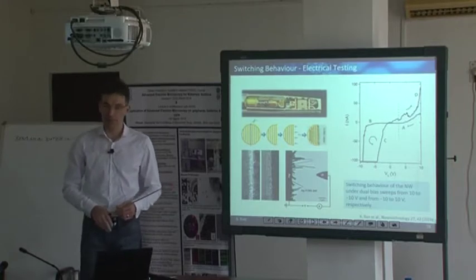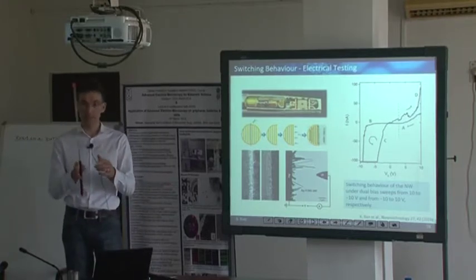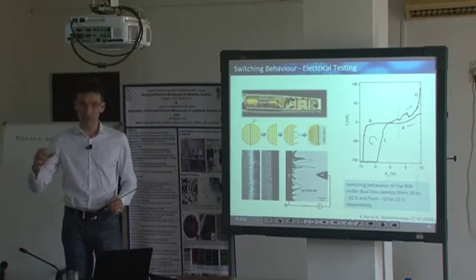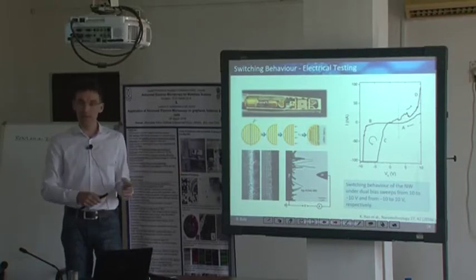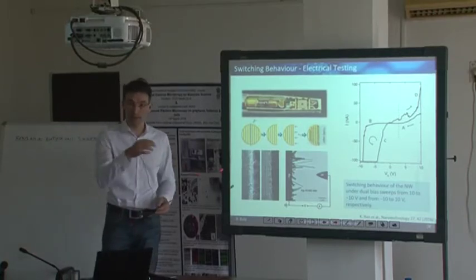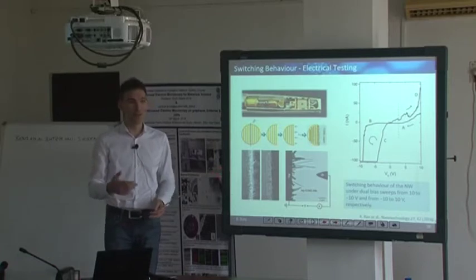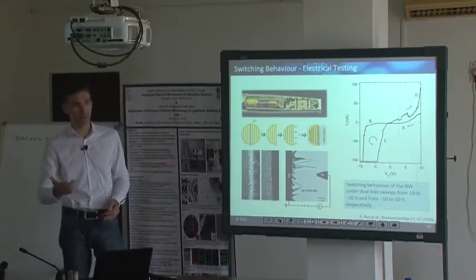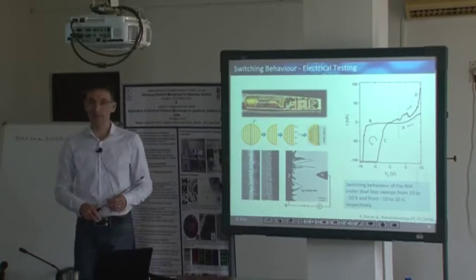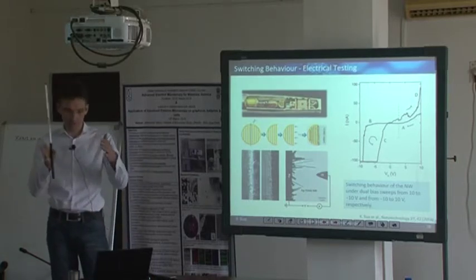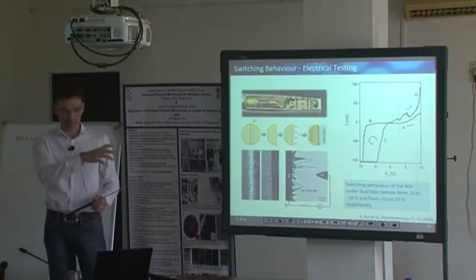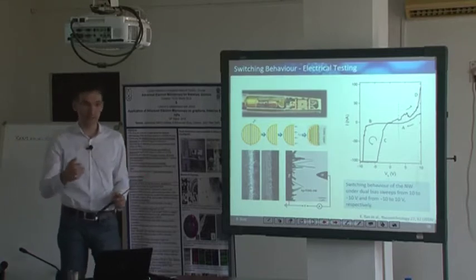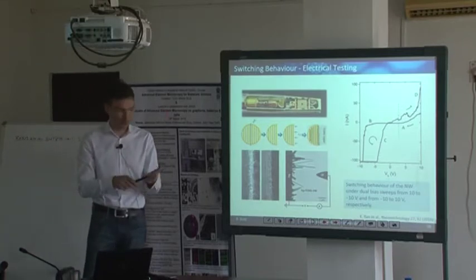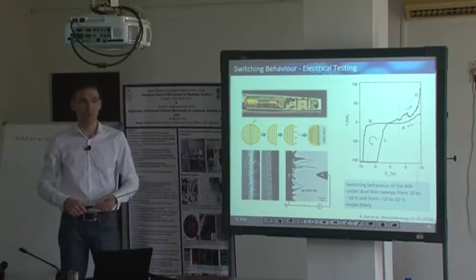And there are people who even prepare TEM samples where your metal channel or your metal contact is confined, and they run a current and they watch this electromigration in real time to see where the failure occurs. And this is quite demanding, because you want to keep all the material intact, just to have your metal channel or your metal contacts embedded in your material while you are penetrating with the electron beam through the structure.